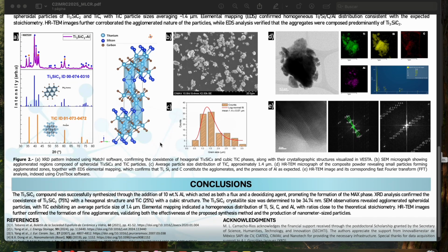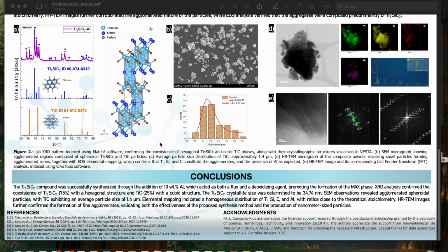The broader impact is a transferable protocol for rapid MAX phase synthesis that can feed directly into property testing. With purity improved, we will move to oxidation kinetics, thermal shock, and device-relevant evaluations to benchmark performance against furnace-based materials. In closing, an Al-assisted magnesiothermic sandwich delivers nanocrystalline Ti3SiC2 at about 75% purity in a 5-minute cycle, with a clear lever set for further improvements. We view this as a practical bridge between exploratory MAX chemistry and scalable processing suitable for aerospace, automotive, and energy components.